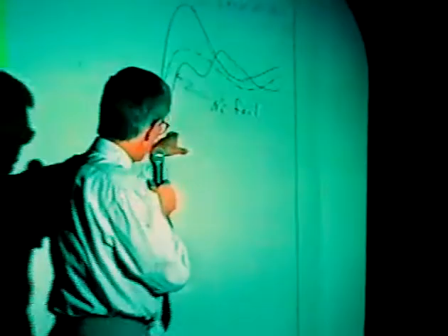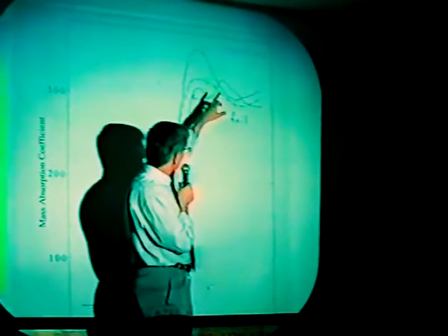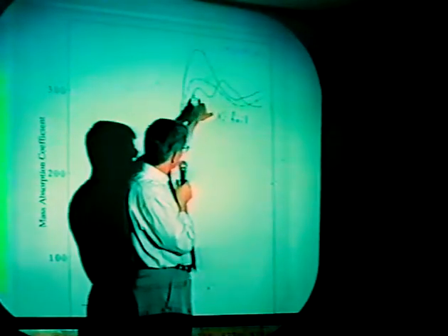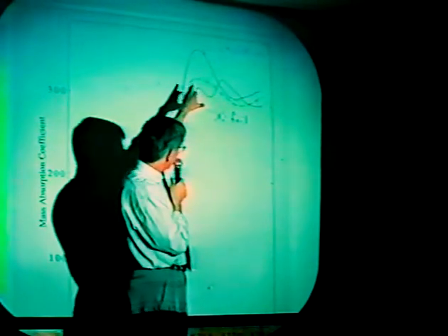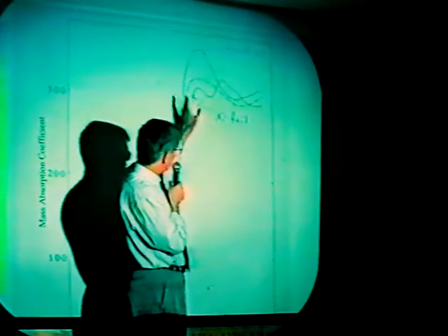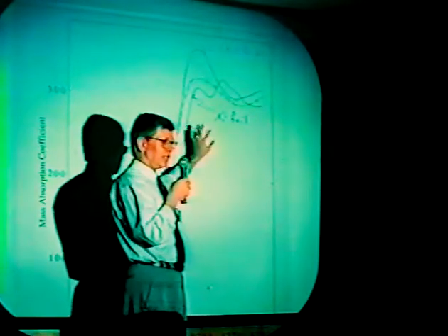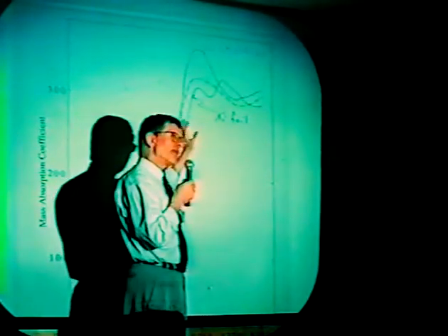So in this case, we're comparing the intensity right at the edge for nickel foil, and as we add nickel to platinum, in fact, that intensity goes up quite dramatically, as it would if there was electron transfer from the nickel to the platinum. Now, I should hasten to add that if you look at the platinum edge, it's not so clear cut. For the L zeolite, we've looked at the whole range of compositions for platinum, nickel, and silica, and then we get the same result.